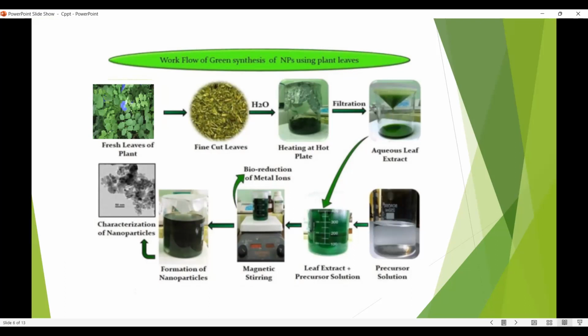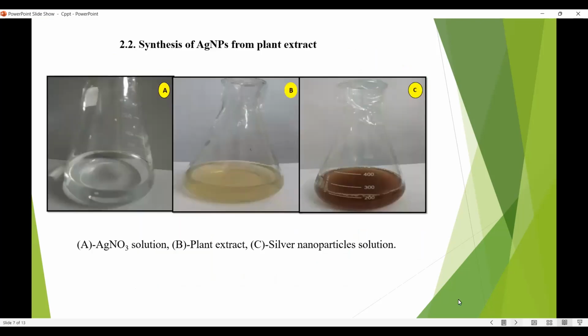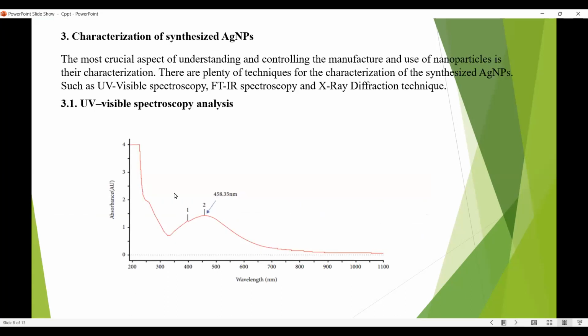The formation of silver nanoparticles is indicated by the color change in the solution. The color change is shown in this figure. This is the colorless silver nitrate solution, and this, figure B, indicates the plant extract. By adding these two, we get a dark brown colored solution, which indicates the formation of silver nanoparticles. That solution was filtered using Whatman No. 1 filter paper, dried at room temperature and kept in a desiccator for the complete removal of moisture present in our nanoparticles. The obtained nanoparticles were subjected to many characterization techniques. We used UV-visible spectroscopy, FTIR spectroscopy, and X-ray diffraction for the characterization.